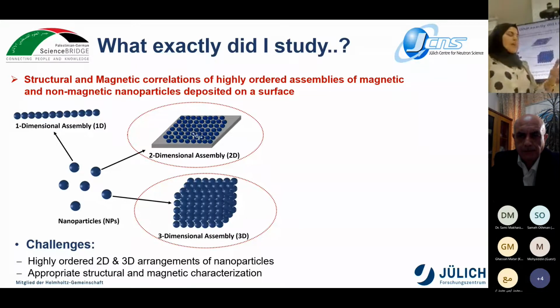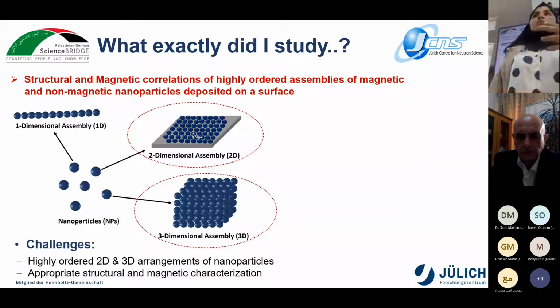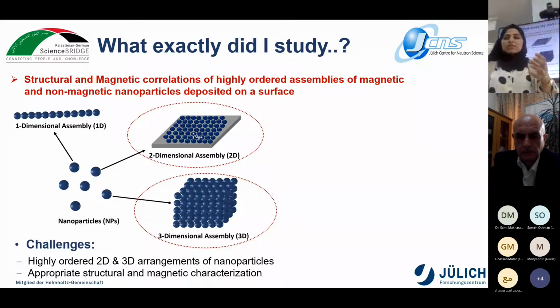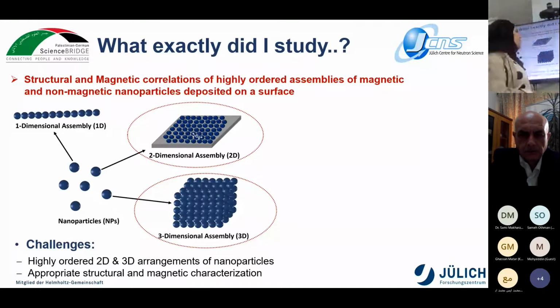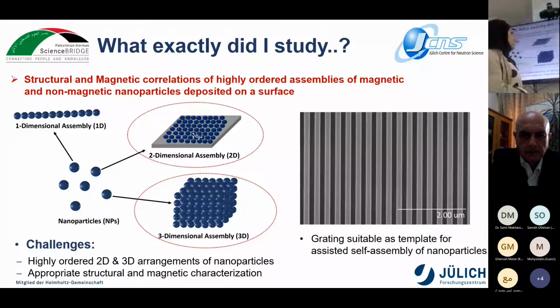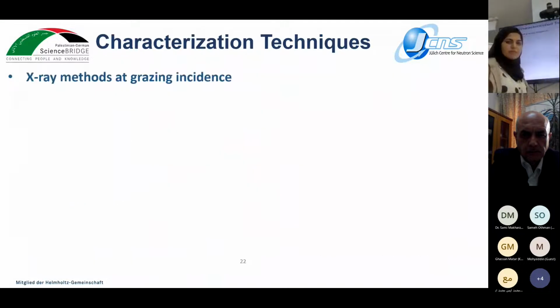The application of nanoparticles is an interesting and exciting topic, but it is only one side of the coin. The flip side is the ability to characterize such a system, to find a suitable technique that provides us with the novel properties of this nanostructured system in the nanometer regime. In order to reach a high coherence of the lateral order of the nanoparticles, I use a template, in my case a grooved silicon grating, because it is suitable as a template for assisted self-assembly of nanoparticles.